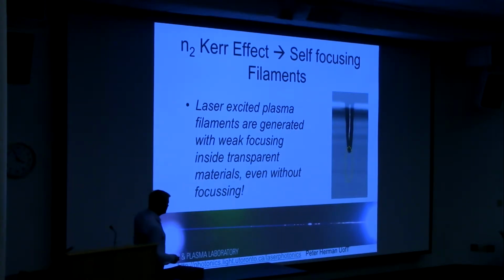And so we discovered a way using bursts to enhance this effect, that we can make really long filaments, one burst at a time, and then eventually we could make these curtains of filaments at meters per second. And in, for example, Gorilla Glass, which is already stressed, those filament tracks just pop the material apart. Or in other cases, you apply a little pressure and the plates separate. And so this technology took quite a few years to develop, but eventually it's now today replaced in diamond saws, which seems like a cheap technology.